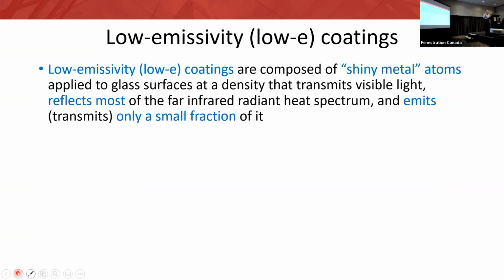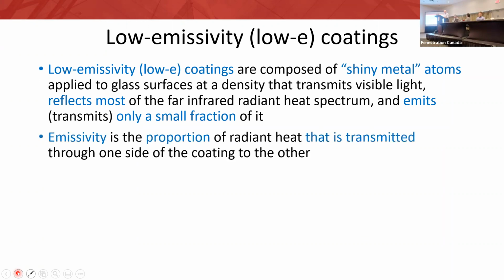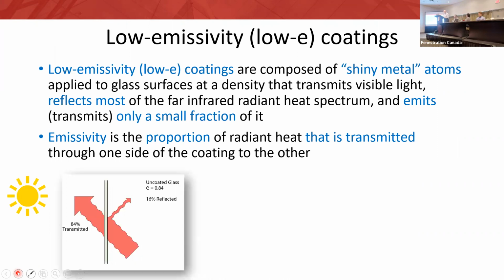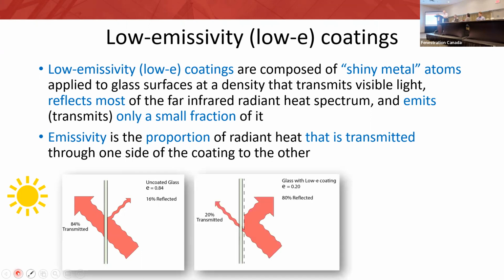And so only a small portion of that radiant heat actually is making it through that coating. The property called emissivity is the proportion of radiant heat that actually makes it past that low-E coating. It's transmitted to the other side. And some of you will know some of these facts, but ordinary uncoated float glass transmits about 84% of the heat energy. It only reflects 16% back into the room. So you've got an emissivity of 0.84.